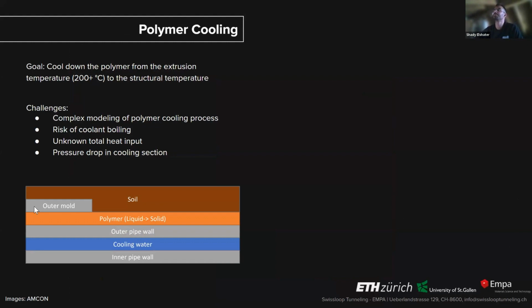Final main challenge, the polymer cooling. I already mentioned it a few times earlier, but really we want to bring down the polymer from the extrusion temperature down to the structural temperature. Modeling the cooling down is quite complex because you have empirical heat transfer models. You have risk of coolant boiling, because if you use water, and at the start you have your polymer at 200 degrees, then the average of the two temperatures, meaning the wall temperature, could be very close to 100 degrees. And then also the pressure drop in the cooling section.